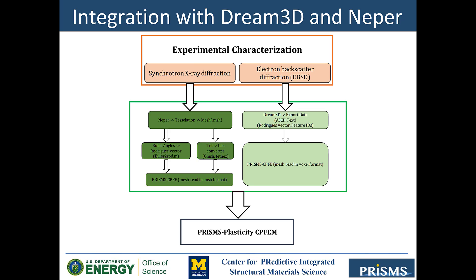Finally, the pipeline generates the required input file for PRISMS-Plasticity — an orientation file in Rodrigues vector space and grain ID. Alternatively, one can use the open-source software Neper to link material characterization to PRISMS-Plasticity, which is especially useful for generating microstructure from grain-by-grain data obtained from synchrotron X-ray diffraction. Note that PRISMS-Plasticity CPFE code can handle structured and unstructured hex elements. If you have a TET mesh, you should use a TET-to-hex converter included as a utility within the code. Additionally, Neper outputs orientations as Euler angles, which must be converted to Rodrigues vectors using a MATLAB script freely downloadable as utility software from the main GitHub repository.